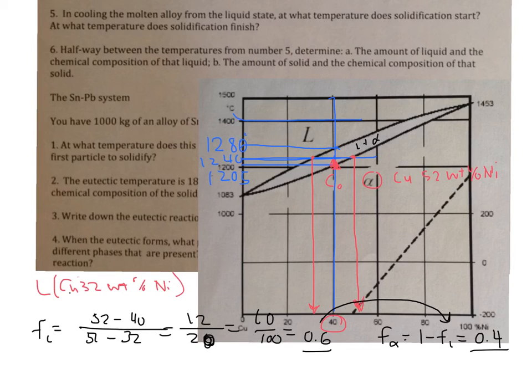So what we have here is the amount of the liquid. The amount is 0.6 times, we remember that we have 500 grams, so 0.6 times 500 grams. What we have is 600 grams, that's not right, 0.6 times 500 is 300, 300 grams liquid.